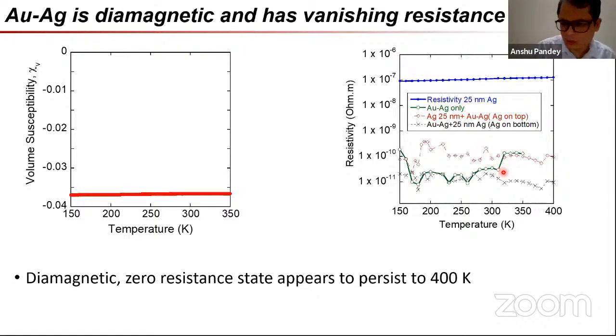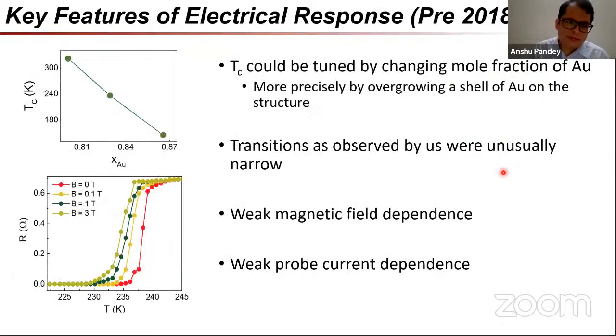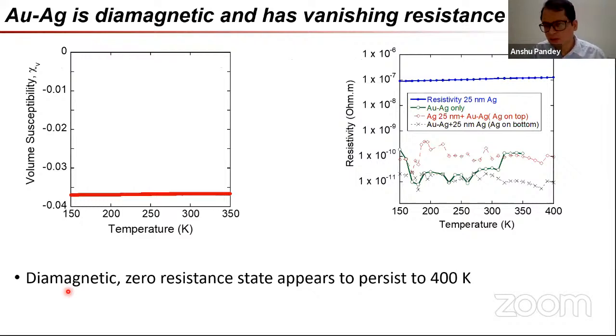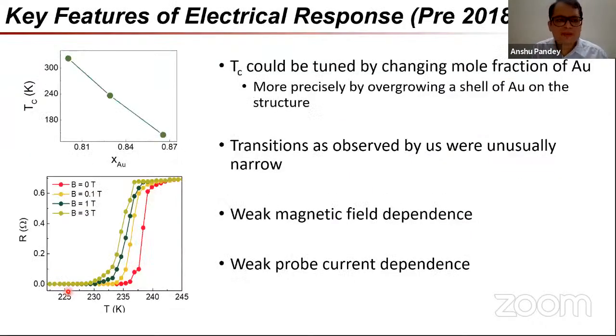Meant that even, whatever its internal structure be, its actual resistivity was far lower than silver's. And that made it interesting to us. We found that we could change the temperature at which it sampled this low resistance state. So again, what we observed in the early measurements was always a zero resistance state. But then we were able to tune the mole fractions of gold within these materials.